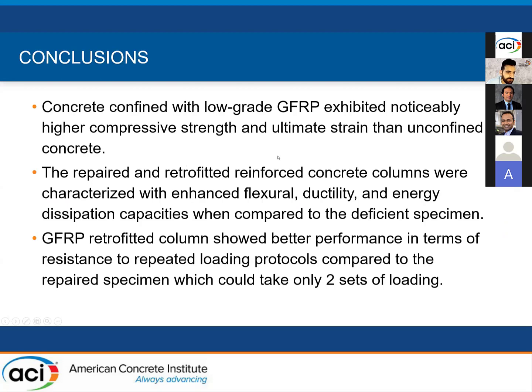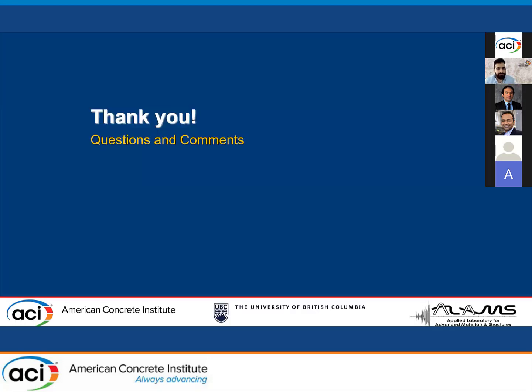So the key conclusions from this study are that concrete confined with the low-grade GFRP considered in this study exhibited noticeably higher compressive strength and ultimate strain than unconfined concrete. The repaired and retrofitted reinforced concrete bridge columns were characterized by enhanced capacity, ductility, and energy dissipation when compared to the deficient specimen. The GFRP retrofitted column showed better performance than the repaired one when subjected to repeated cyclic loading protocols. Thank you, and I would like to take your questions.